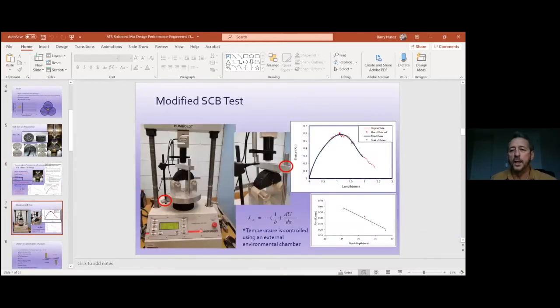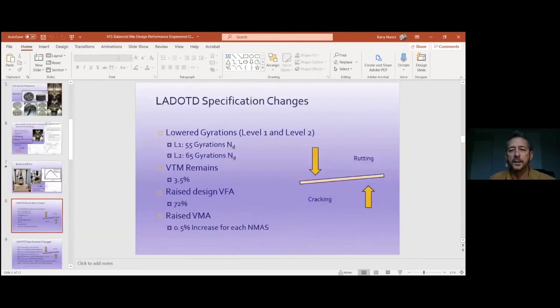This is some more slides on looking at some of the curves and the fixtures being used. And once again, Sam reviewed this, so I won't go too deeply. We did drop our gyrations. We held on to 3.5% air voids, where other states, where they're truly doing a balanced mix design, start at 4, or they just do the rutting and cracking test and find the optimum asphalt content using those parameters.